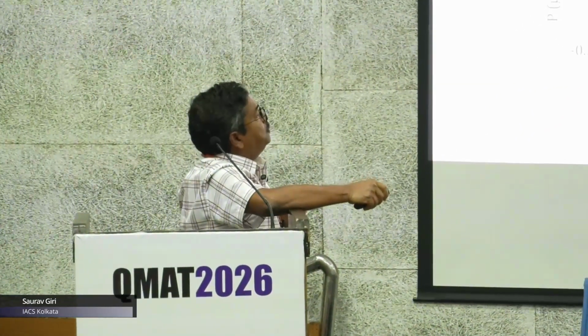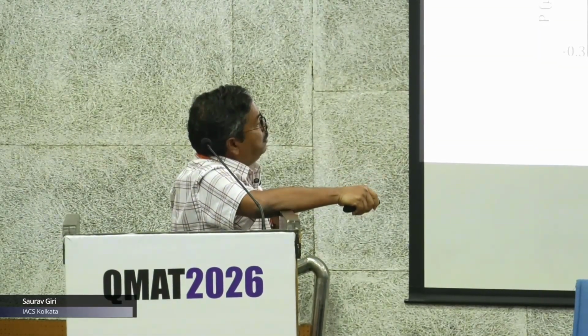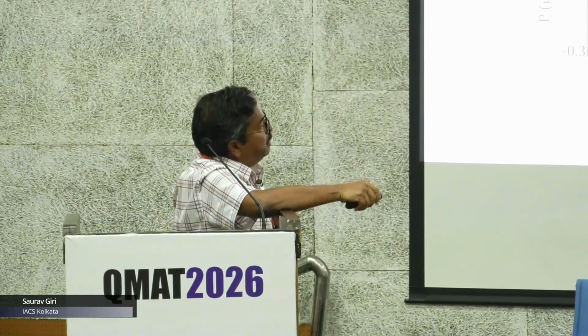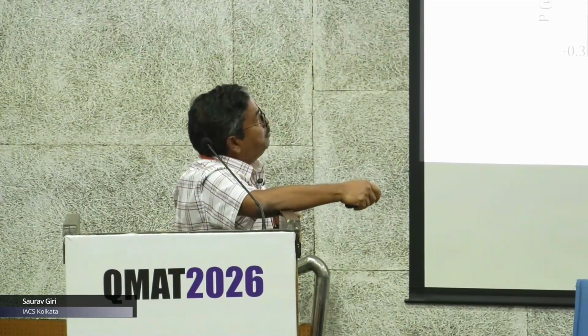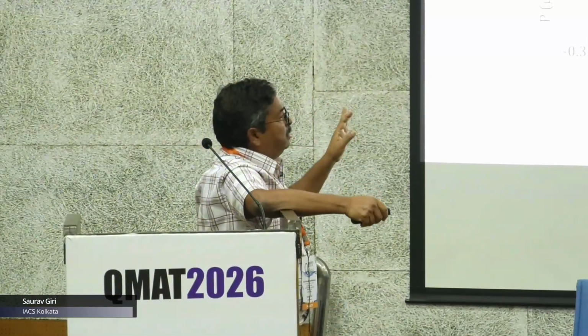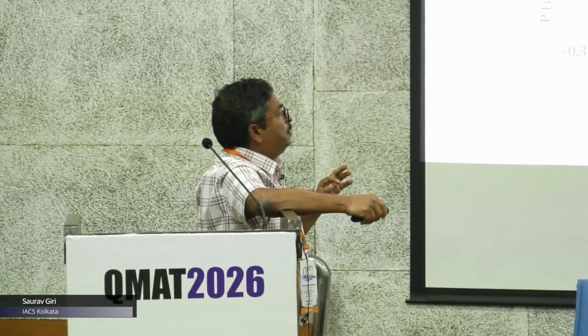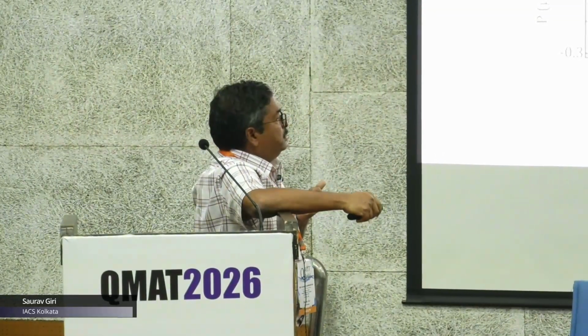A similar measurement was done for the terbium ferrite. We observed the high temperature ferroelectric order, and we also observed the low temperature ferroelectric order below the terbium ordering temperature, where the magnetization also shows a well defined peak. So we have two ferroelectric orderings for the terbium compound. The established report so far was that ferroelectricity can appear below the rare earth ordering temperature, which we observed here.